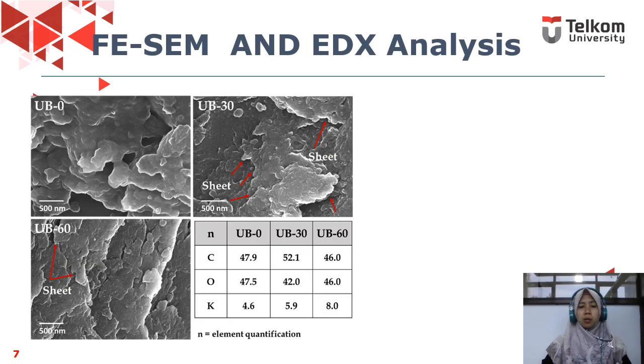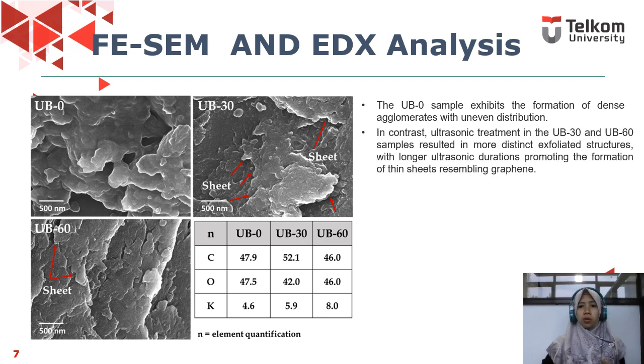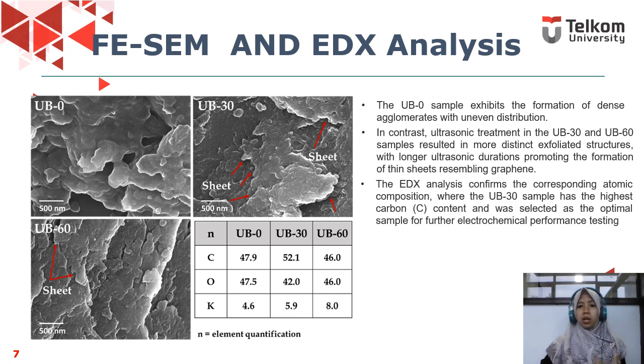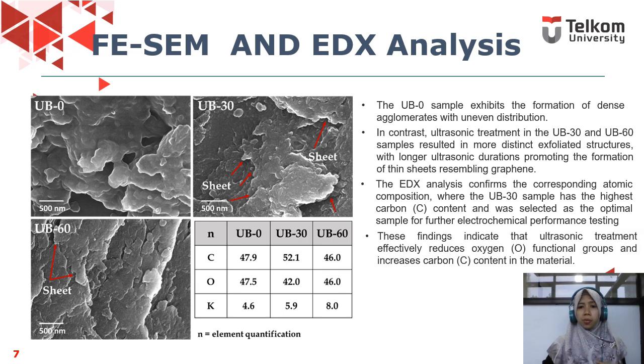This is the SEM and EDX analysis. The UB0 sample exhibits the formation of dense agglomerates with an uneven distribution. In contrast, ultrasonic treatment in the UB30 and UB60 samples results in more distinct exfoliated structures, with longer ultrasonic duration promoting the formation of thin sheets resembling graphene. The EDX analysis confirmed the corresponding atomic composition, where the UB30 sample, which has the highest carbon content, was selected as the optimal sample for further electrochemical performance testing. This finding indicates that ultrasonic treatment effectively reduces oxygen functional groups and increases carbon content in the material.